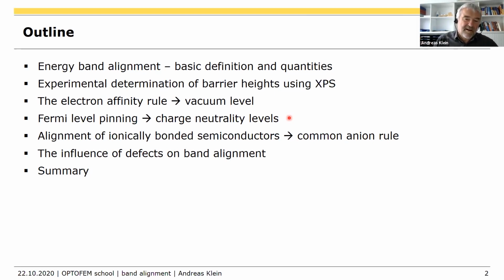These materials have a quite strong covalent character of their chemical bonds. And I will show you that this Fermi level pinning by induced gap states is particularly important for these covalent semiconductors, and it's less, or in principle not, relevant for the ionically bonded materials. That includes the chalcogenides and it includes the oxides. Actually, that's a good thing for the chalcogenides because that's really one of the reasons why these materials work so nicely as thin film solar cell materials.